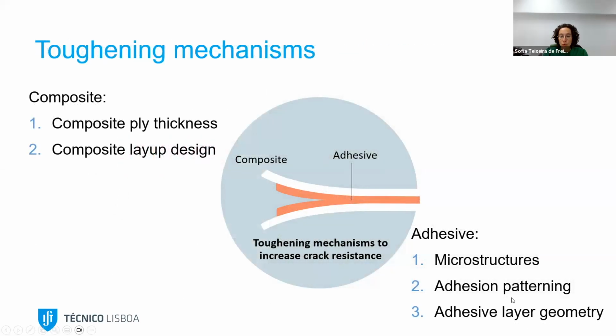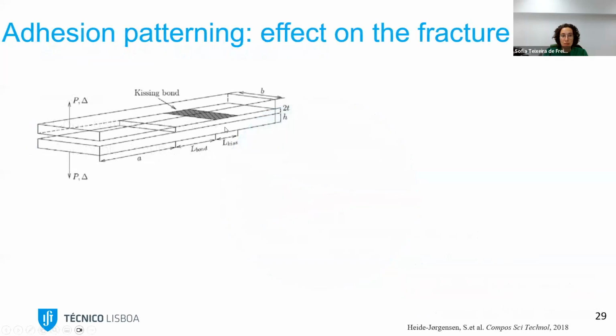Now we can also do something with the adhesion patterning. And the adhesion patterning is adding some contaminations in the surface. So using a defect, which I was talking with you about in the beginning, the kissing bond. So this is the contamination area of the adhesive. And try to see, can this be used in our favor to toughen the adhesive?